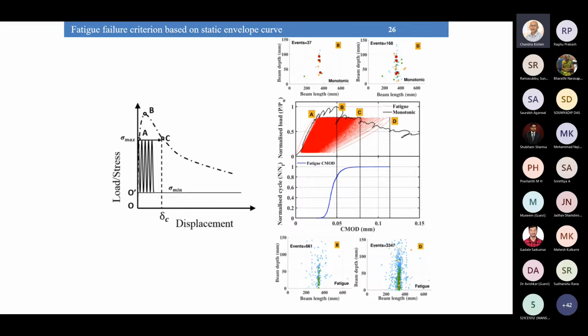The static envelope curve states that the monotonic or quasi-static response of the specimen, which is shown here by the dotted line, serves as a bound for either the displacement or the strain values for a specimen subjected to fatigue loading. So this implies that the failure strain, or the failure displacement, can be obtained between this sigma max and this minimum. When the sigma max hits the static curve, this is considered as a failure criterion under fatigue.